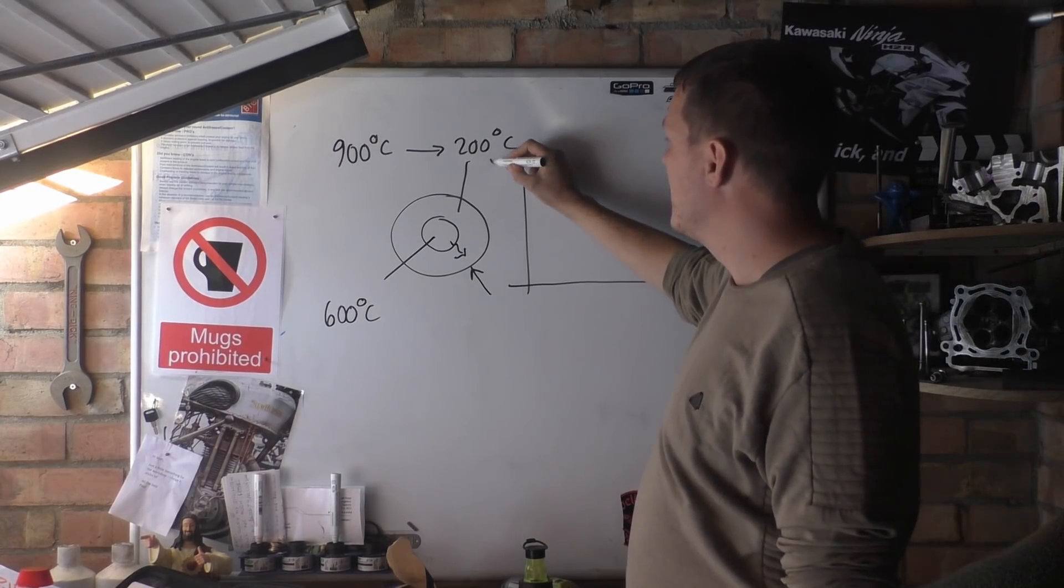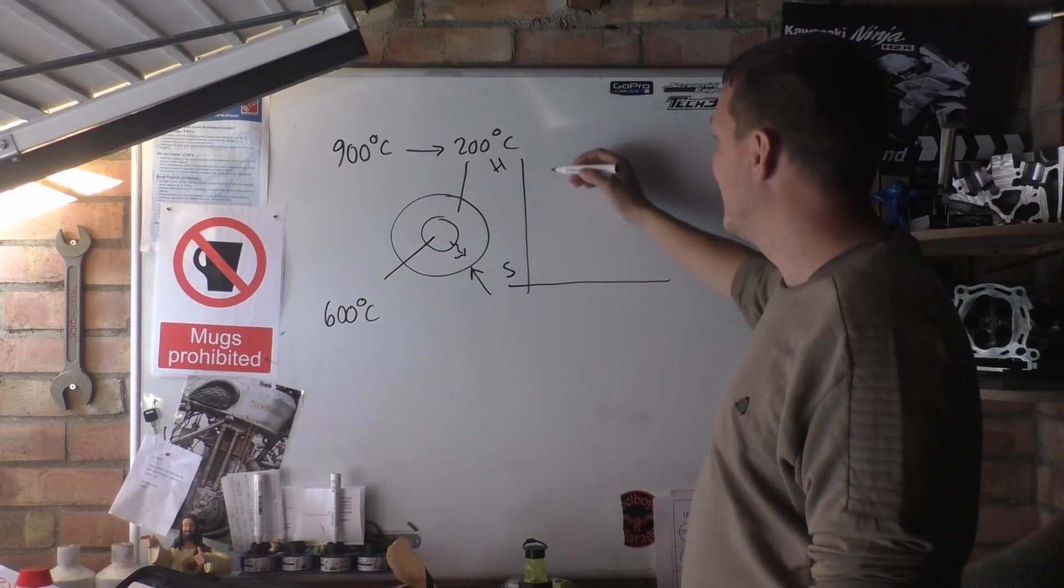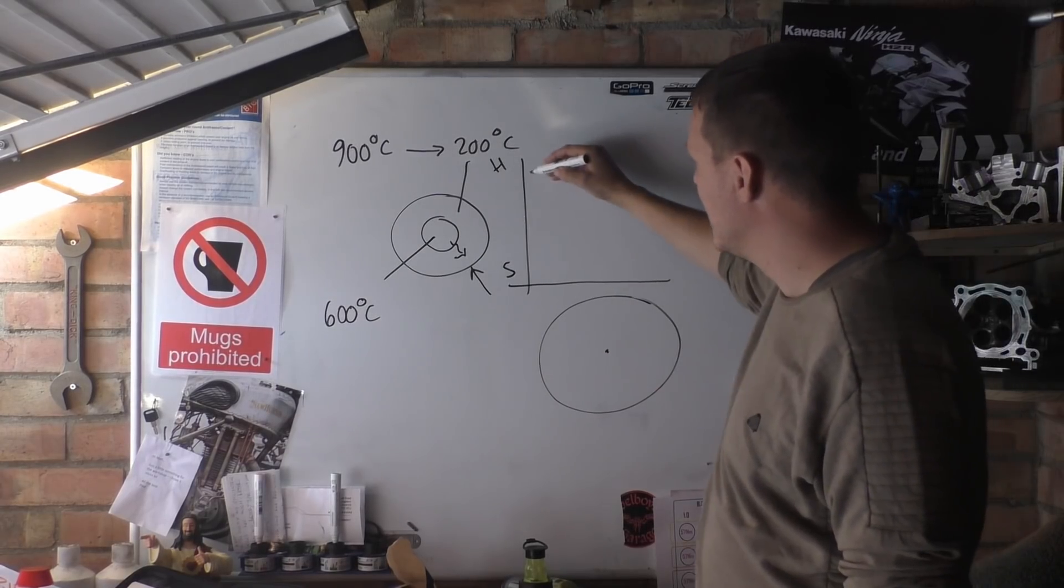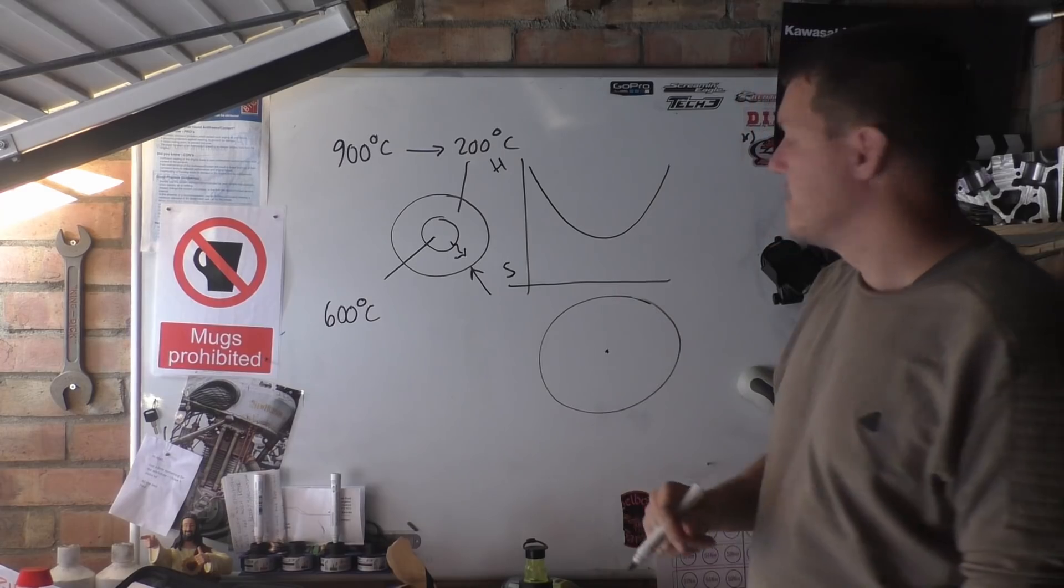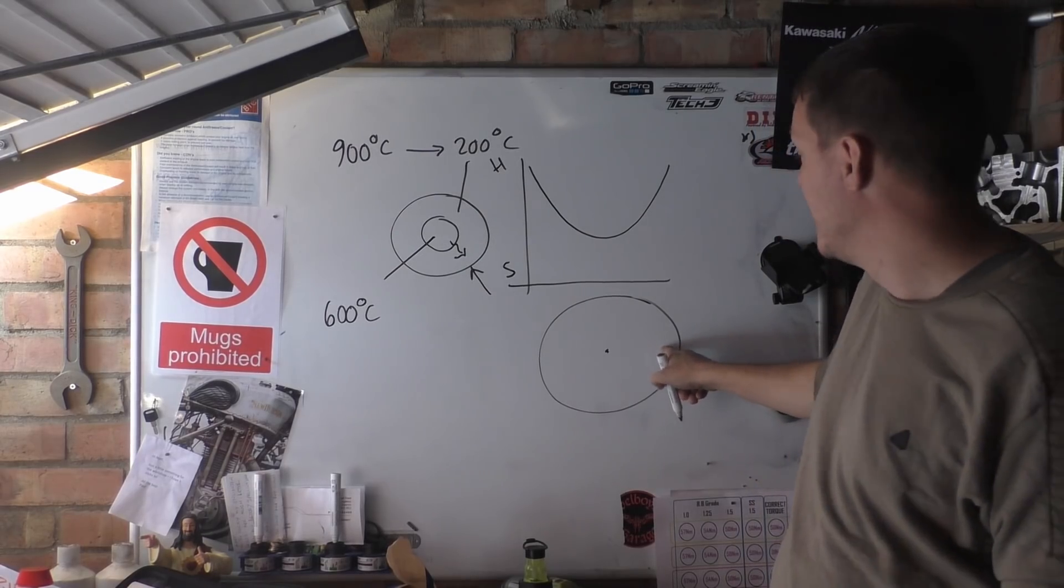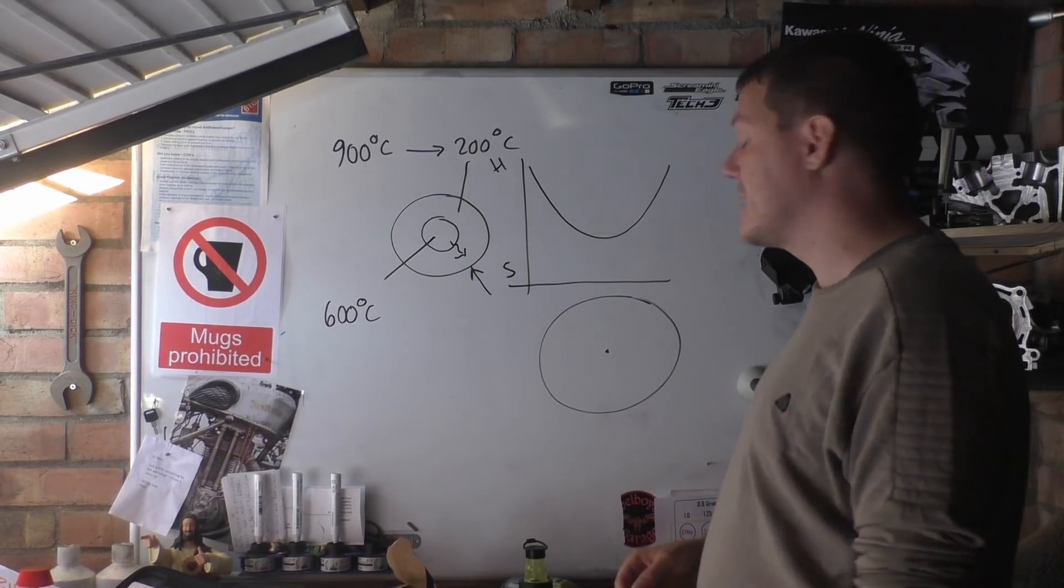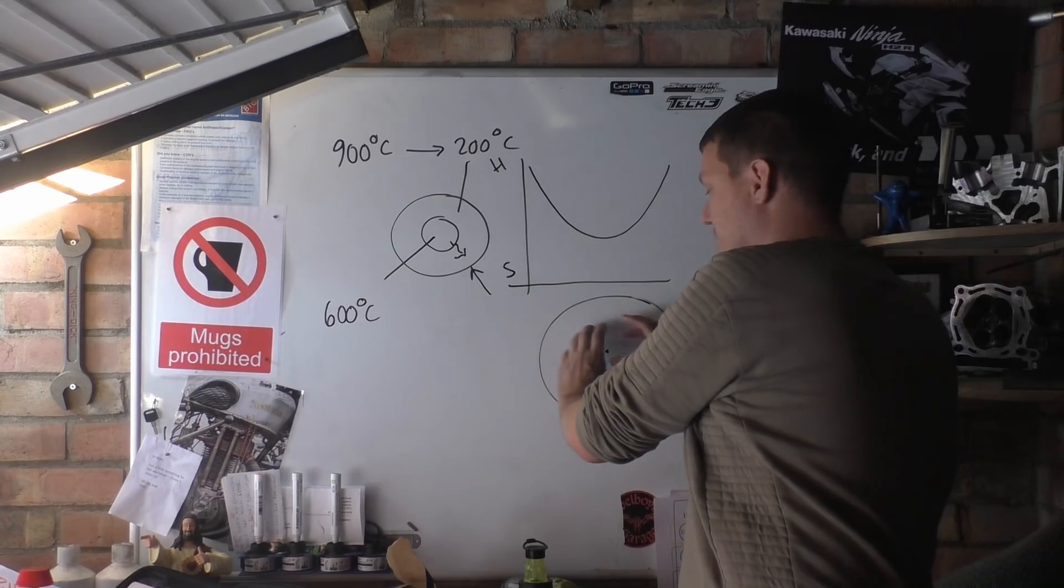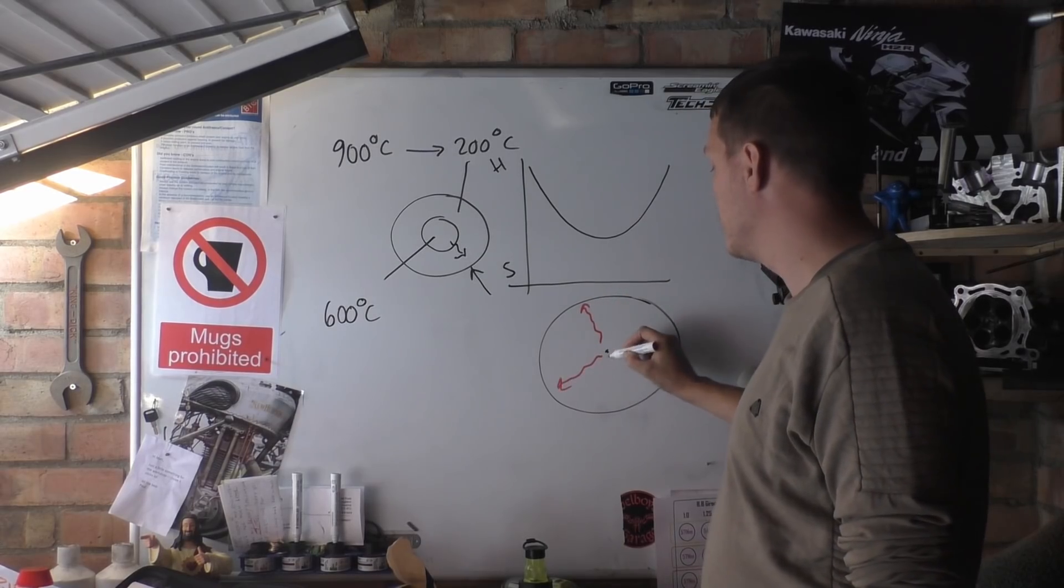If you could plot out, this is hard, this is soft, as you go through the cross section of this steel, so there's the center region, you'll basically get something that's like this where it's hard on the outside, it'll get softer towards the center, and as you go further out to the outside perimeter it gets hard again. Great, it's almost like surface hardening. Great, it's not through hardening. But you've got to remember this is with through hardening - you are dropping in water, the water will cool down the outside and slowly cool, or the energy, the heat will pass outwards to the colder regions.